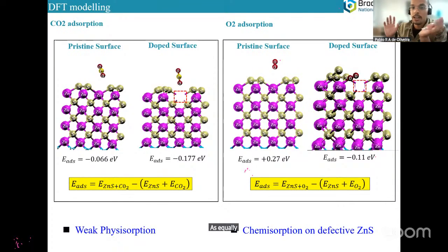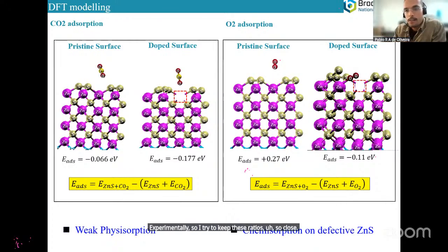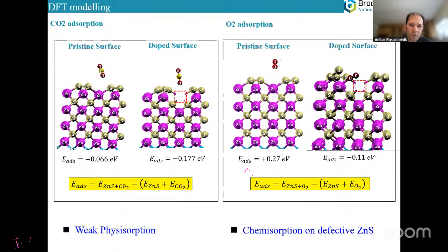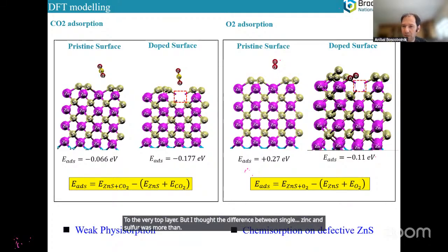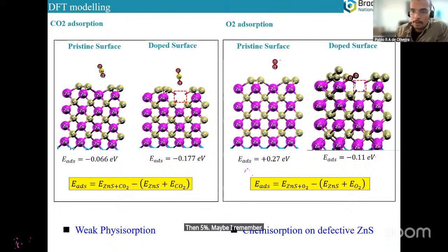Exactly. I'm supposed to have below 5% of defects experimentally, so I try to keep these ratios close. I thought it was larger from the experiment, at least from the XPS, which is not necessarily surface sensitive to the very top layer. But I thought the difference between zinc and sulfur was more than 5%. Maybe I remember. No, you have 16 atoms of zinc, 16 atoms of sulfur. No, in the experiment, I mean. In the experiment, I don't know.